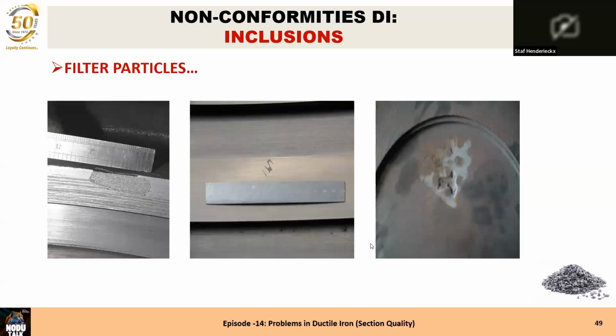And this is filter particles. You can have on the left side nearly a complete filter which came, for one reason or another, inside the casting. That seldom happens. In the middle, you can see a small part of a filter which broke off and went with the metal inside the casting. And your customer will definitely not be happy with that, because his machining tools will be broken on this particle. It's so hard that it will be breaking. And on the right side, you see somewhat bigger than the middle one, smaller than the other one. But you can be sure that filters which are not properly added or properly, let's say, produced, you can get a problem with them as an inclusion.